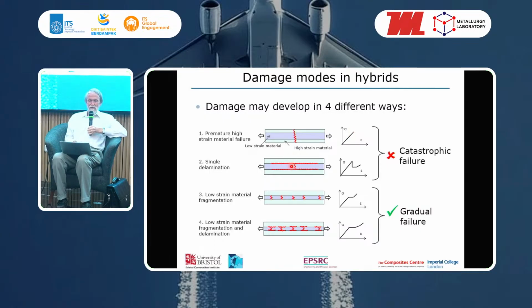So if we reduce the proportion of carbon, and we have less carbon to glass, then when the carbon breaks, there's enough glass to carry that load, so the glass does not break. But if we're not careful, what will happen is you get a delamination at that point. So the carbon will break, it will immediately delaminate, and you'll get a load drop. So again, it is not a gradual failure.